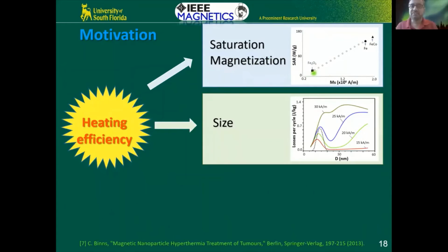Now here's something that shows the SAR in watts per gram, because it's a dissipation, it's a power. And you can see for iron oxide, maghemite in this case, it is very low compared to iron cobalt. Iron cobalt is even better because the magnetization is very high. Unfortunately, iron cobalt is not allowed inside the human body. Only iron oxide, whether it's Fe2O3 or Fe3O4 magnetite, these are the only magnetic materials considered biocompatible. They're approved by the FDA, the Food and Drug Administration. They've been authorized for these kind of therapies.